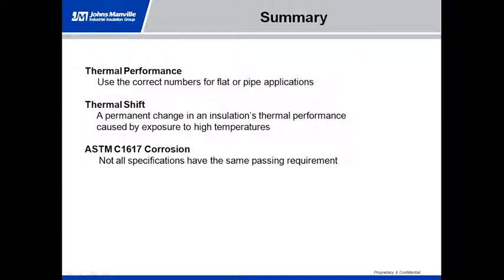And knowing that this occurs, a designer can compensate for the degraded material by adding an additional layer or layers of insulation. So again, you want to use the 3E Plus software and try to figure out how many layers. In our example that we saw at 600 degrees or 800 degrees, we saw that it was one additional layer. Finally, for ASTM C1617, not all specifications have the same passing requirement. Again, it depends on the product type, and there are different passing limits for C1617, and the calcium silicate is the most stringent. Want to make sure that you keep that in mind.